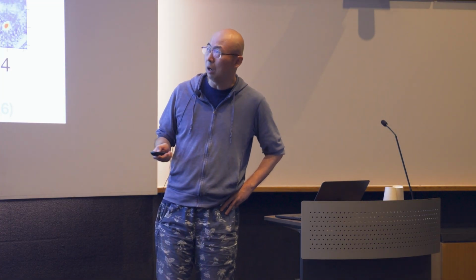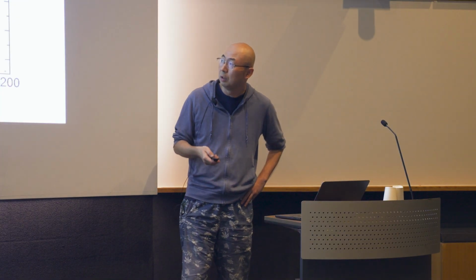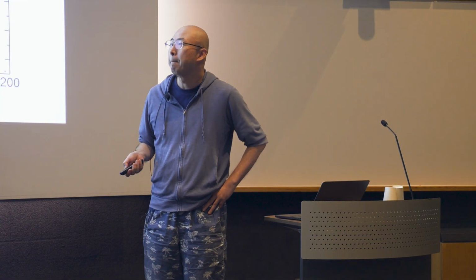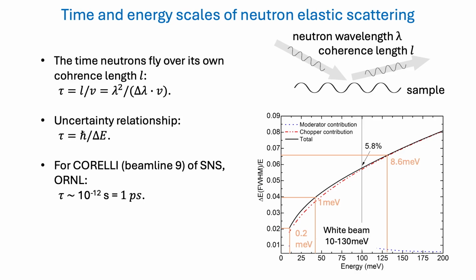All right. So now let's take a break and let's think about what is the meaning of this measurement. So the meaning of this measurement is a neutron scattering of the magnetic ensembles, right? Magnetic correlation. So your sample is a magnetic material, have a spin correlation in the surface and at the bulk. Then you basically have neutron with wavelength lambda coming in, and this neutron does have a coherence length. And the scattering is only meaningful once this neutron flies over its coherence length L.